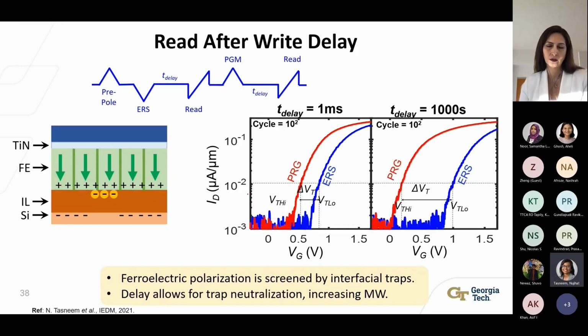On the other hand, as time passes, these trapped charges start getting more and more neutralized, and we see more electrons in the semiconductor channel, which increases the memory window as well. So for example, instead of 1 millisecond, if we had waited 1000 seconds, which is approximately 16 minutes, the memory window we read would have increased from half a volt to 1 volt. So the bottom line is that the memory window increases as read after write delay increases.